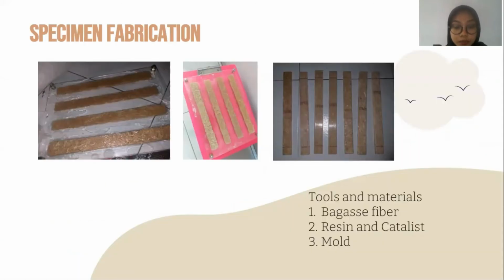The next process is specimen fabrication. In this process, the composition is calculated by volume fraction, with the matrix at 65%. Then the layers are arranged on the mold, and the resin and hardener are mixed in a ratio of 3:1. A mixture of resin and hardener is applied to the layer using a roll, then dried until it hardens, and then the composite is separated from the mold.